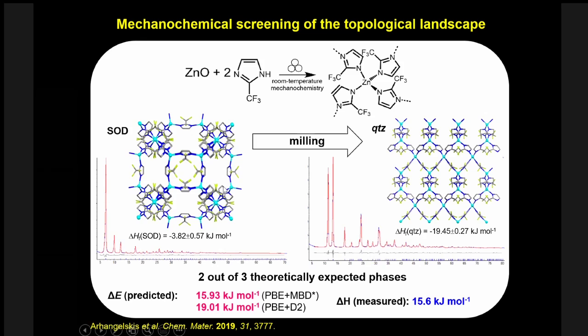And it turns out that if you just grind carelessly, you're going to get this quartz material, which is more stable. But if you grind gently and you add, let's say, a liquid phase during your milling that can occupy the pores of the MOF, you can actually stabilize this open framework structure. And the difference between them is measured, again, thanks to the Navrotsky team, roughly 16 kilojoules per mole.